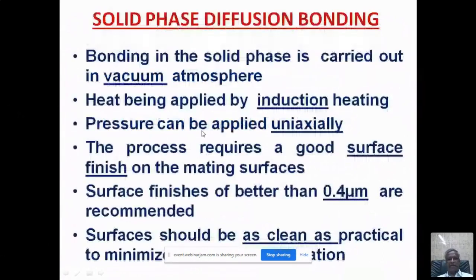For solid phase diffusion bonding, normally you require a vacuum atmosphere. The air will be completely sucked out. Vacuum should be maintained, and the heat is supplied by induction heating, along with pressure. So these are the main things: you require vacuum, heating, and pressure. Then the process requires a good surface finish on the metal surface, normally in the range of 0.4 microns. The surface should be as clean as possible.